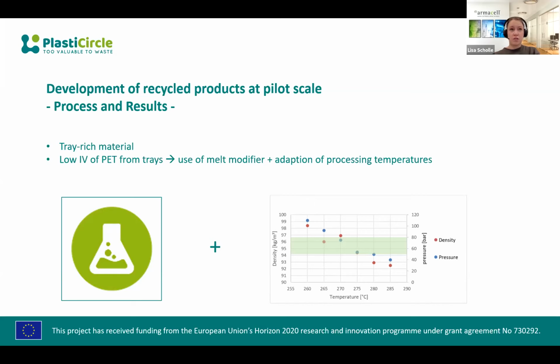We developed a melt modifier formulation that allows to maintain melt pressure while preventing material degradation. On the right graph, you can see the impact of the temperature on the pressure. This was tested in a range of 260 to 285. And you can see here, too low temperature leads to high pressure and therefore to an unstable process, while too high temperature leads to low pressure, which makes the foaming insufficient. The best result could be achieved with a temperature around 270.